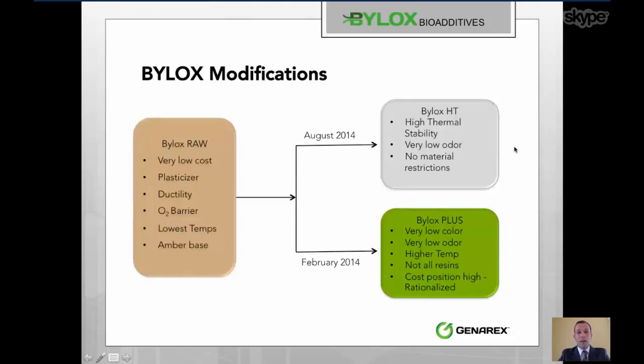And Bylox HT, our newest iteration as of August 2014, has actually seen several new technological breakthroughs since then, where we've raised the thermal stability ceiling, we've reduced the odor signature and found ways to neutralize the odor signature altogether, and we found ways to couple, blend, and work into different miscible or different systems through all sorts of different conversion technologies, be they injection molding, extrusion, film, blown film, cast, profile, really any type of process, with the lone exception being rotomolding, because our products, just like any additives, don't melt by themselves and as such don't tend to stick very well.